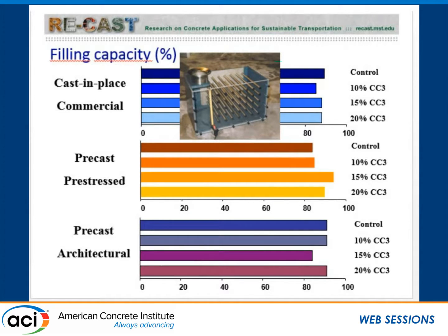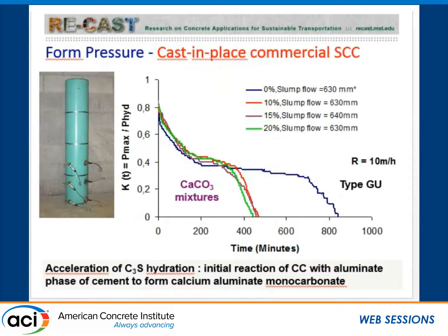And the number that we usually see in recommendations for highly reinforced structural sections, for example, in earthquake moment-resisting frames where you have a lot of lateral reinforcement, is 80% and above. So these concretes, these SCC, obviously are developed to be extremely workable. And we see that the limestone filler, whether you use it or not, is not really affecting the passing ability much. It's already very good. It's not hindering it either, which is important.